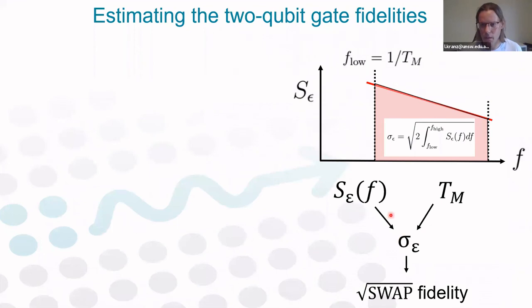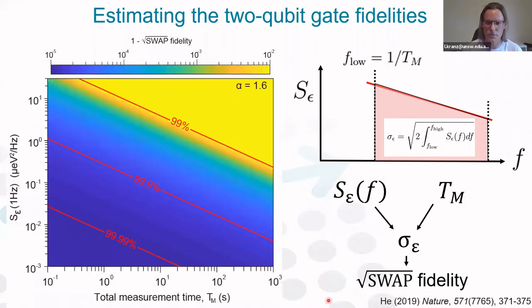Well, we can measure the noise spectrum, and then if we can estimate the total measurement time, we can basically calculate this integrated noise sigma epsilon. And based on that, we can go a step further and think, okay, what kind of fidelities of the qubit gates can we expect given this level of integrated charge noise? So what I'm showing here is the result of such modeling for a square-root SWAP gate. This is square-root SWAP gate fidelity as a function of total measurement time and the noise in your device.